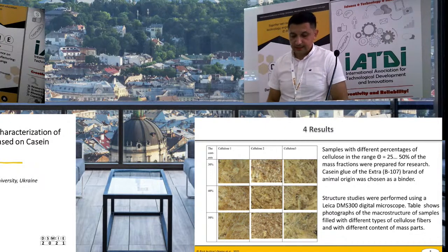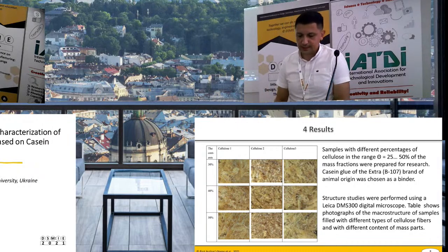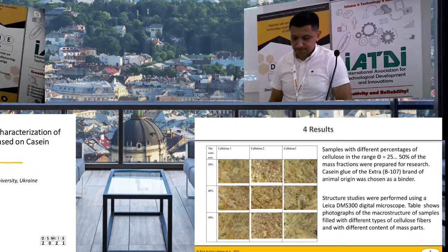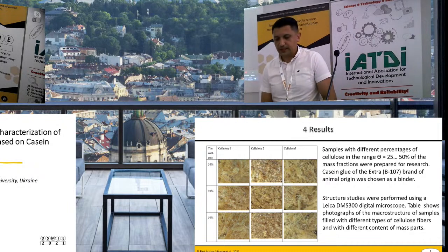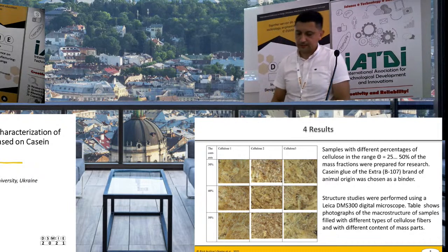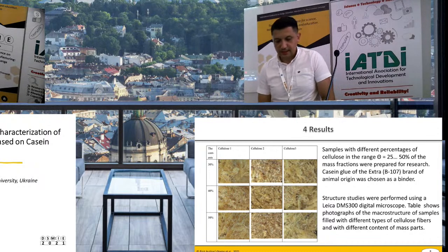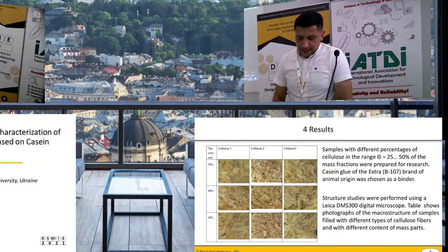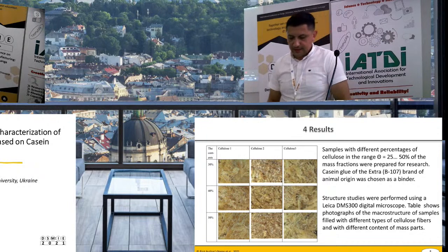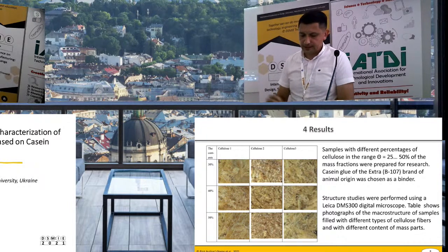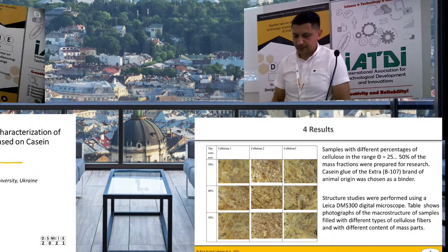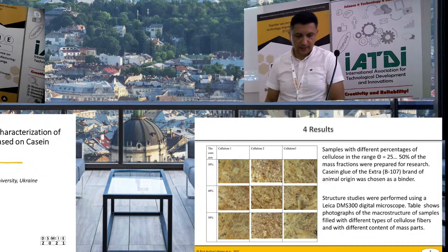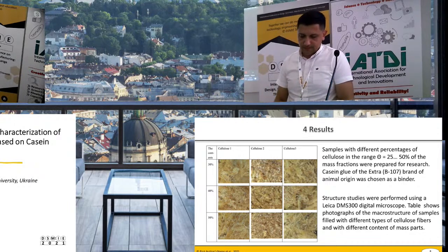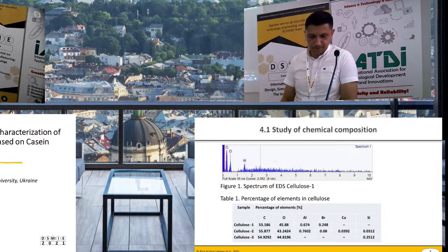To prepare the adhesive solution, the powder was gradually poured into water at room temperature with constant stirring. Then the resulting mass was placed in prepared aluminum molds, dimensions 10 by 10 by 100 millimeters. Please, next slide.